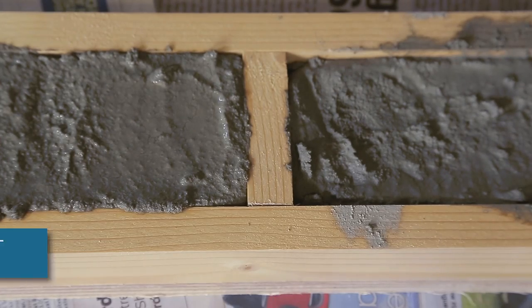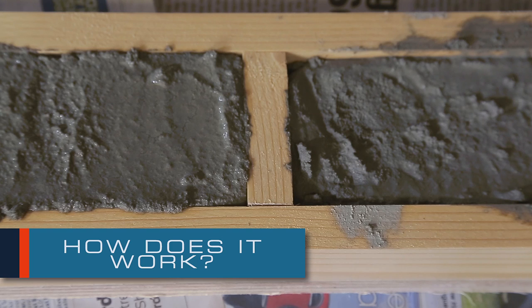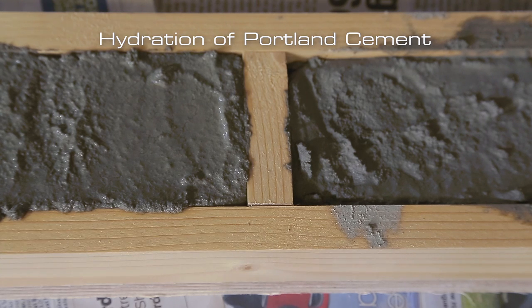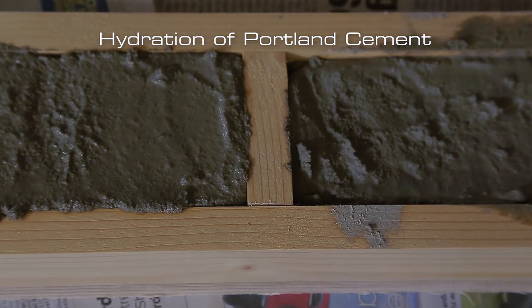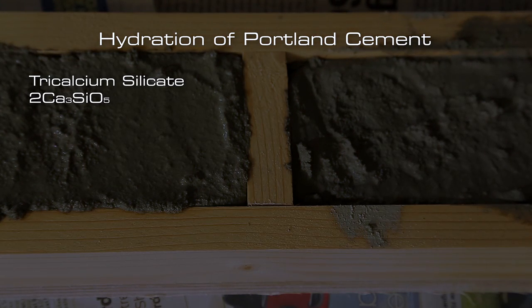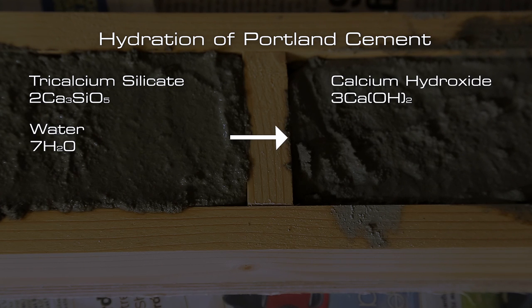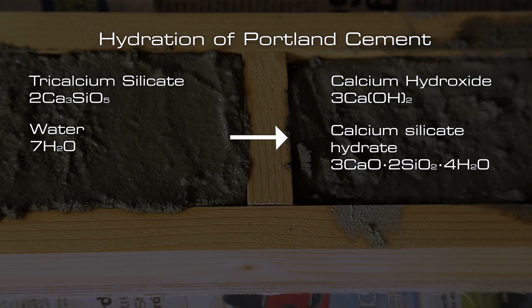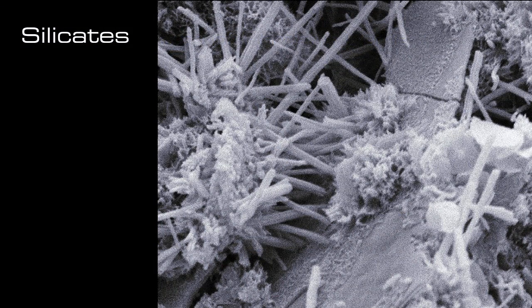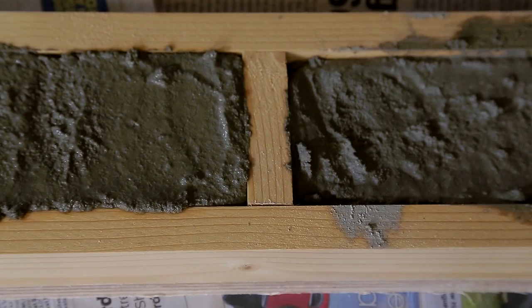When water is added to the cement in concrete, it undergoes a process of hydration. But what is the chemistry behind this? The most important reaction is this. The calcium silicates in the concrete react with the water to form calcium hydroxide and other silicates. These silicates have long, thin, needle-like spikes which interlock with each other, sticking the aggregate together and making the concrete strong. Keeping the concrete wet allows it to cure fully, with all the calcium silicates reacting to form a strong